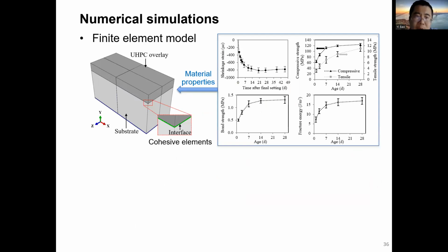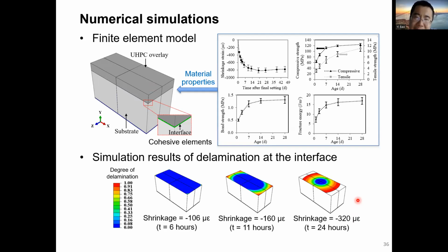In this model, we used the material properties obtained through the material testing. And as you can see, the material properties change over time, right? So if we apply the material properties to this finite element model, we could predict the stresses at interface. And also, if we have the interfacial properties of the interface, then we could predict whether delamination will happen. And if it happens, what is the severity?